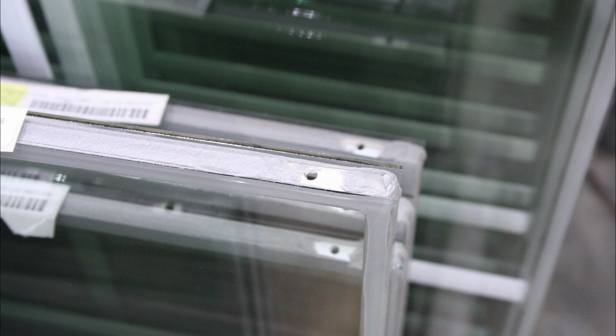Prior to patching, ensure that the units have cooled down to ambient or room temperature. Sealing a unit that is too warm will create a negative pressure inside the unit as it cools, concaving the glass and deflecting it inwards towards the middle of the unit. This puts a constant stress on the glass and may result in a thermal stress crack, which will typically originate at a chip or other glass edge defect.